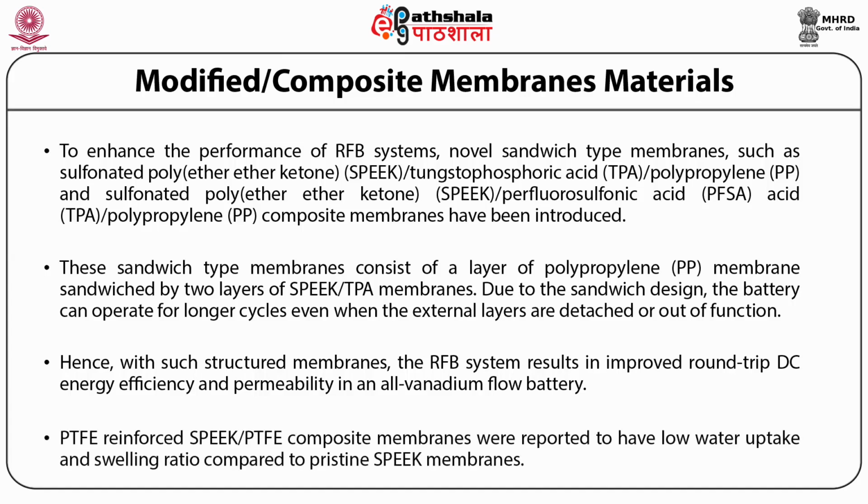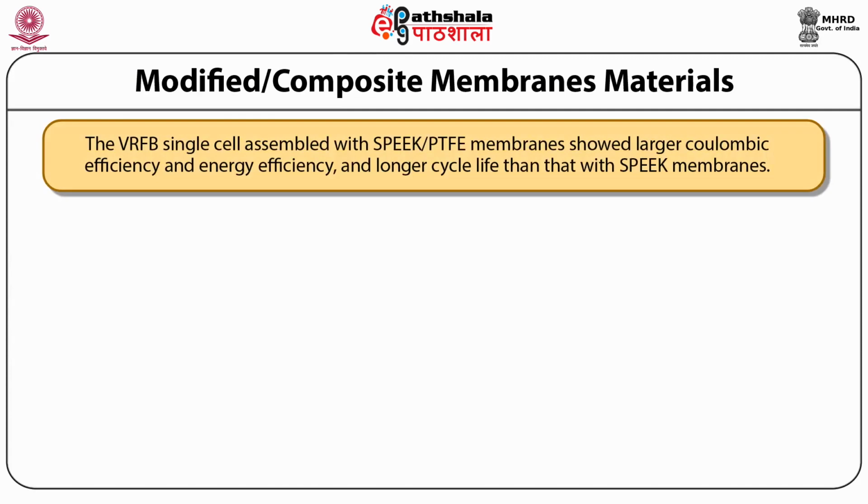PTFE reinforced SPEEK or PTFE composite membranes were reported to have low water uptake and swelling ratio compared to pristine SPEEK membranes. The VRFB single cell assembled with SPEEK or PTFE membranes showed larger coulombic efficiency and energy efficiency and longer cycle life than that with SPEEK membranes.